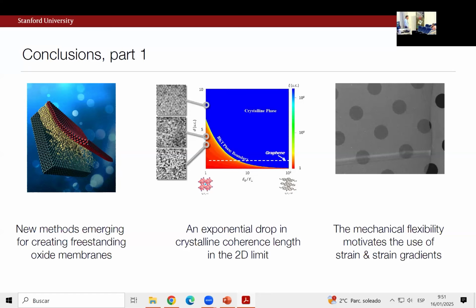Yeah, I think that's a very good point, that there is a lot of hydroxide formation and surface chemistry going on. I should be careful to say that I probably don't know enough about bismuth ferrite, but if anything, it's not obvious to me that it should be more robust to this kind of chemistry than, say, strontium titanate.